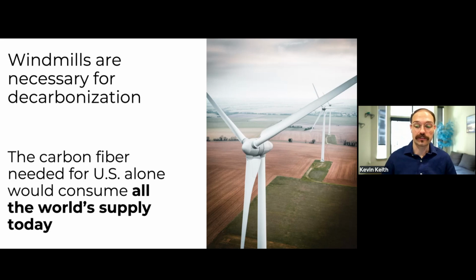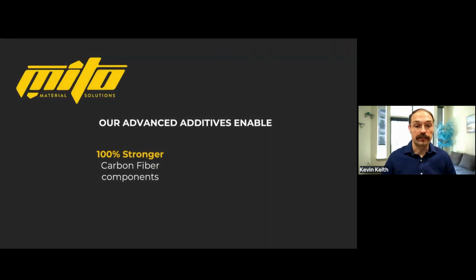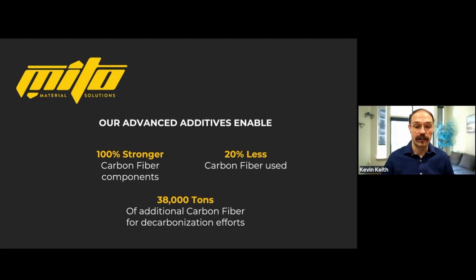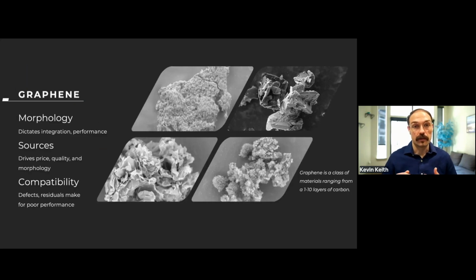And so MITO Materials saw this problem, and we realized that there was one of two ways to really solve that. It was either more carbon fiber needs to be made, and if they're already capped, then there's really not much else that can be done there, or you can do more with less. And so with our additives and our chemistries, we're able to make carbon fiber composites up to 100% stronger at extremely low dosages. So you can use 20% less carbon fiber, and then that way, across the globe, you can reduce the amount of carbon fiber used by 38,000 metric tons. Now, we do this by functionalizing a material called graphene.